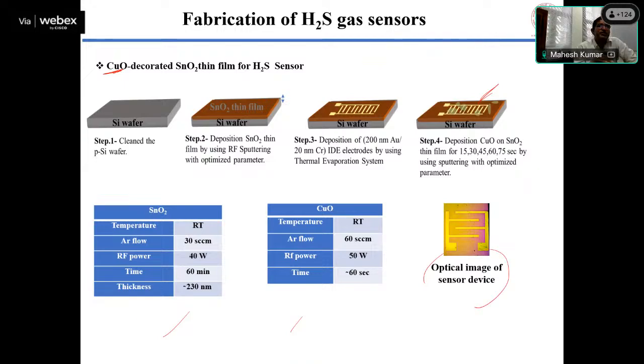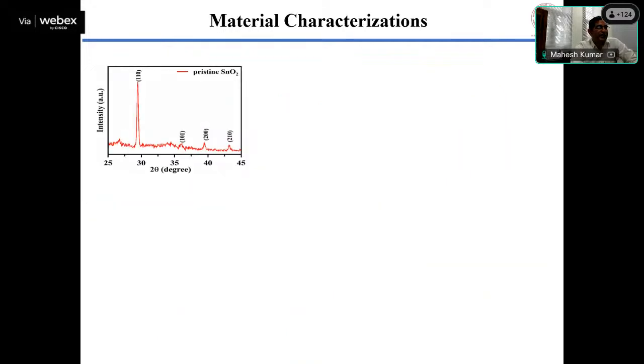What we do is, first we deposit these materials on simple silicon wafers and do all the processing. Once we finalize the best parameters, we deposit on alumina, because here we are using an external heater. In our measurement setup, we have the heater, so as per requirement we can vary the temperature and do all these measurements. But to make a prototype, we deposit this on a silica tube, and then we make the heater.